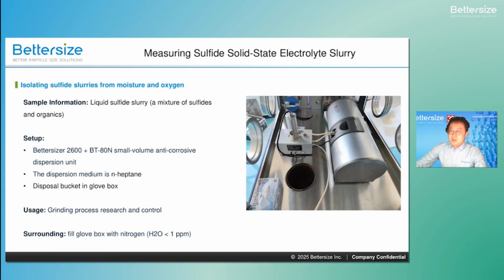Now, let's look at the wet dispersion setup, which is critical for monitoring the grinding process of sulfide slurries. We use the BT-80N small volume units here. This is a strategic choice because it drastically reduces the consumption of expensive anhydrous heptane. Notice the disposal bucket integrated directly into the workspace. This is crucial for safely draining the hazardous solvent waste immediately after testing, without ever breaking the inert nitrogen atmosphere.